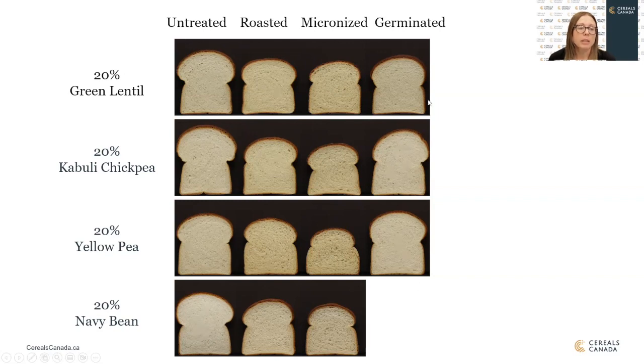So even though they look very good, the germinated flours would not be acceptable in this application of pan bread. The flavor components for the micronized and roasted samples were better, especially the roasted. They had some nutty type flavors and some of them were less bitter. However, micronized samples would not be good in this application either, just because of the low volume and poor crumb structure.